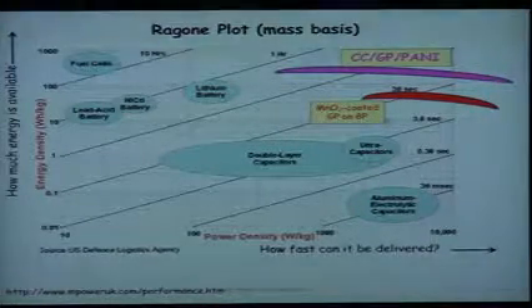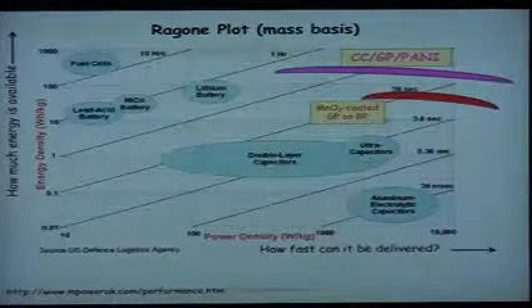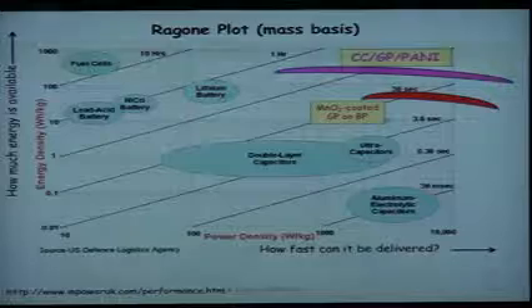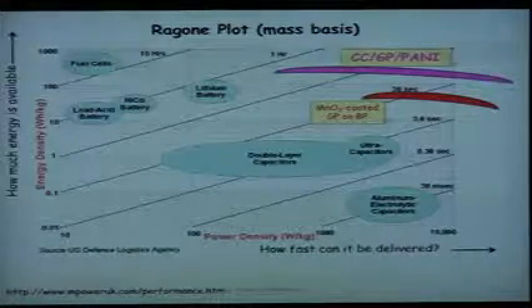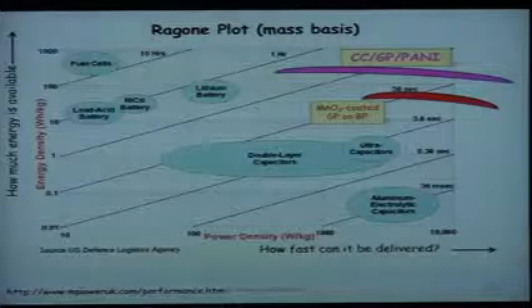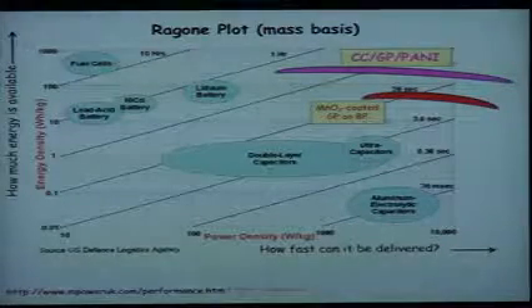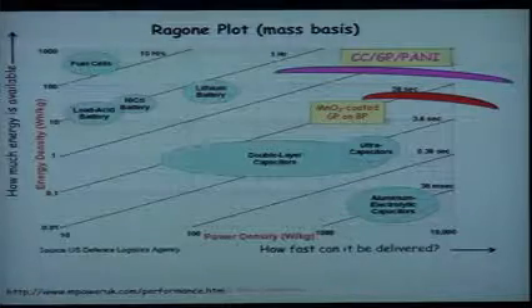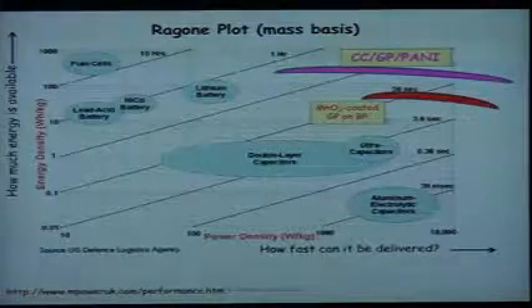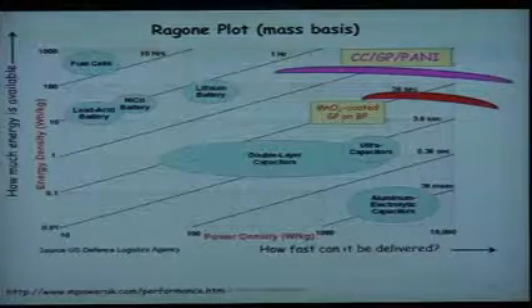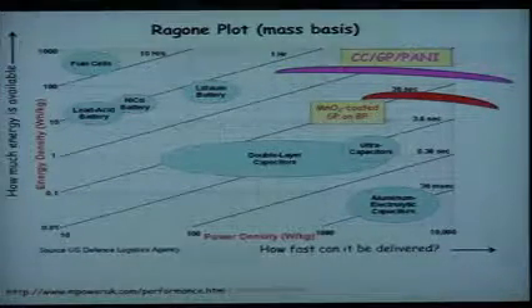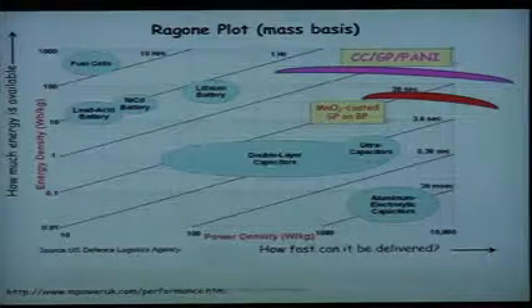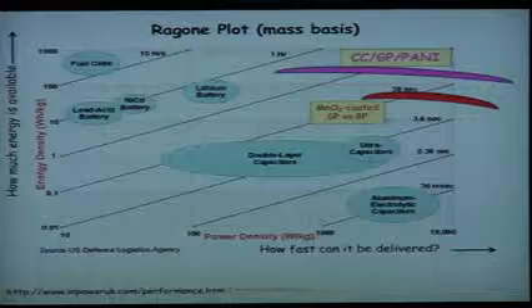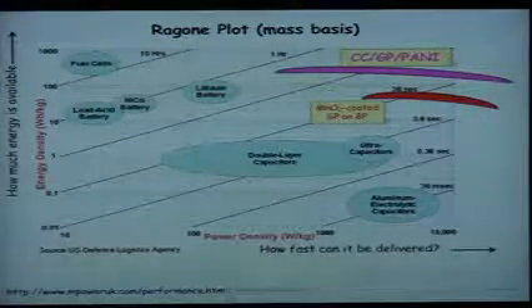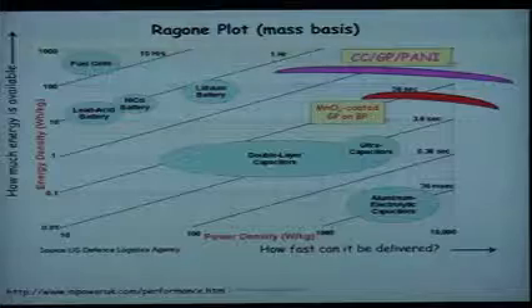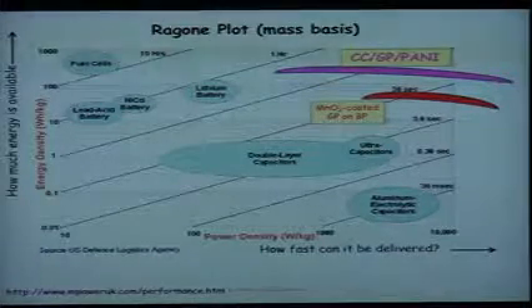Okay. But look at the comparison to the PANI-based, that's the polymer-based pseudocapacitive material, and the manganese oxide. And here we're talking about the PANI-based material. If you look at the middle of the purple curve where that line intersects, you could look at the system here. This number 36 is coming from the fact that we're converting seconds into hours. It comes from 3600. So we had 3.6 seconds, 36 seconds. The next one would be, what would that be? 360 seconds. So that's 6 minutes. That's what that line corresponds to. And then you have an hour.